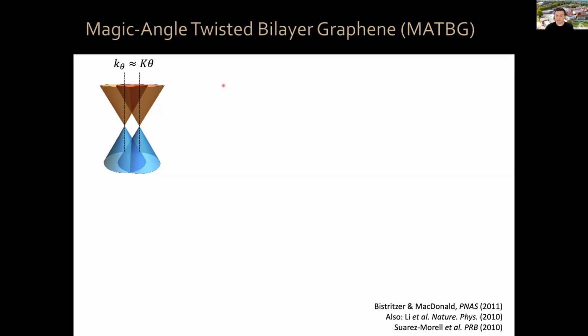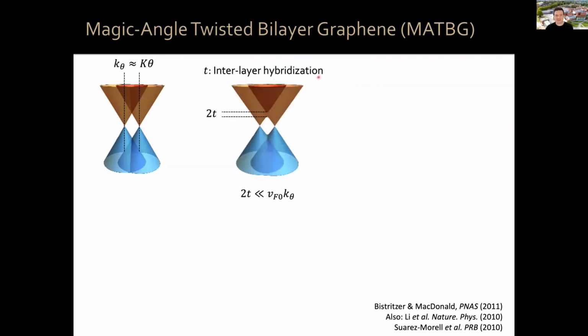However, when we put two graphene sheets on top of each other, they are just 3 angstroms apart. So the electrons are very much aware that they can go from one sheet to the other. They can tunnel. This interlayer hybridization leads to a gap opening here. Bonding and antibonding, this is similar to bonding and antibonding states in the hydrogen molecule, but in this case, it's, if you want, a graphene molecule. So one of these bands gets pushed down to very low energies.